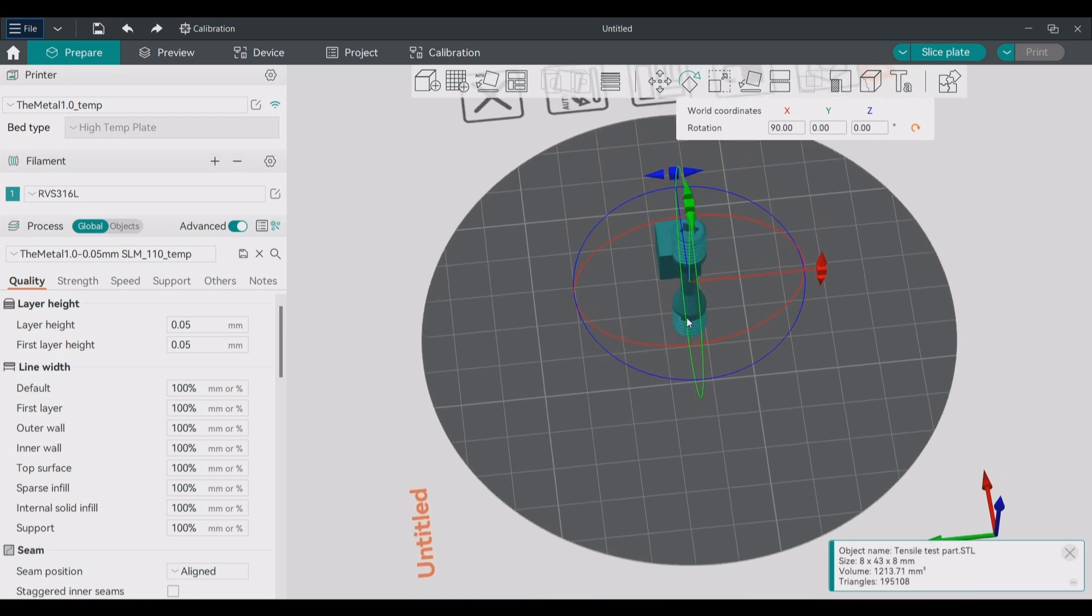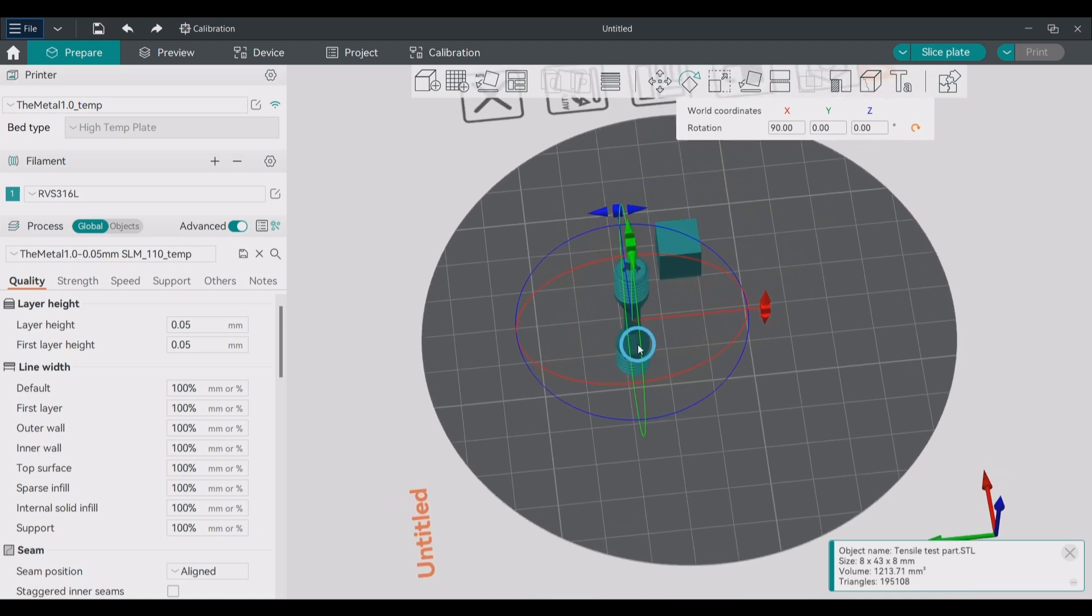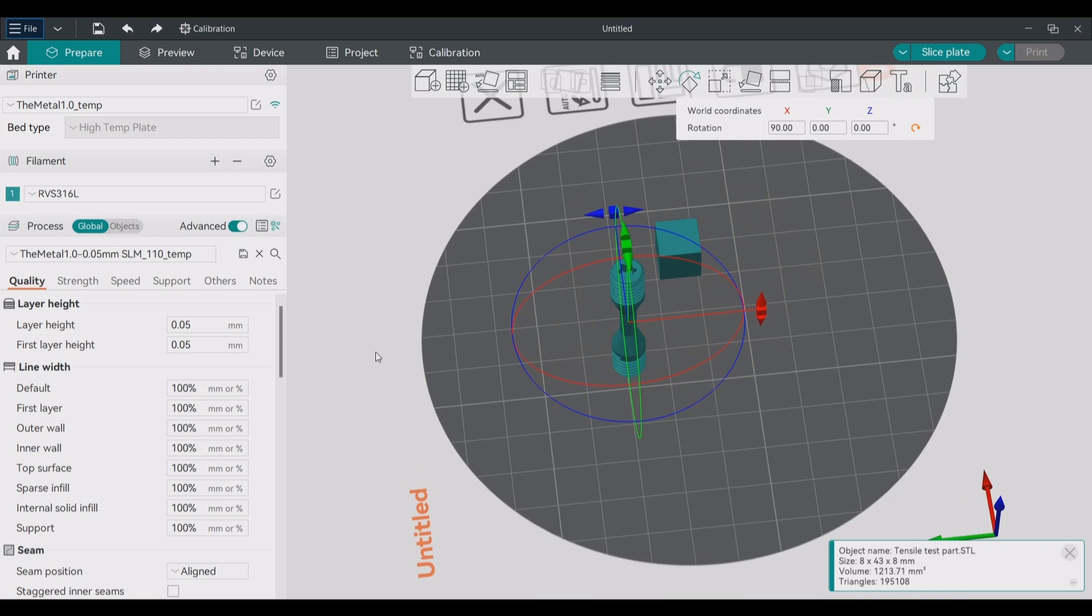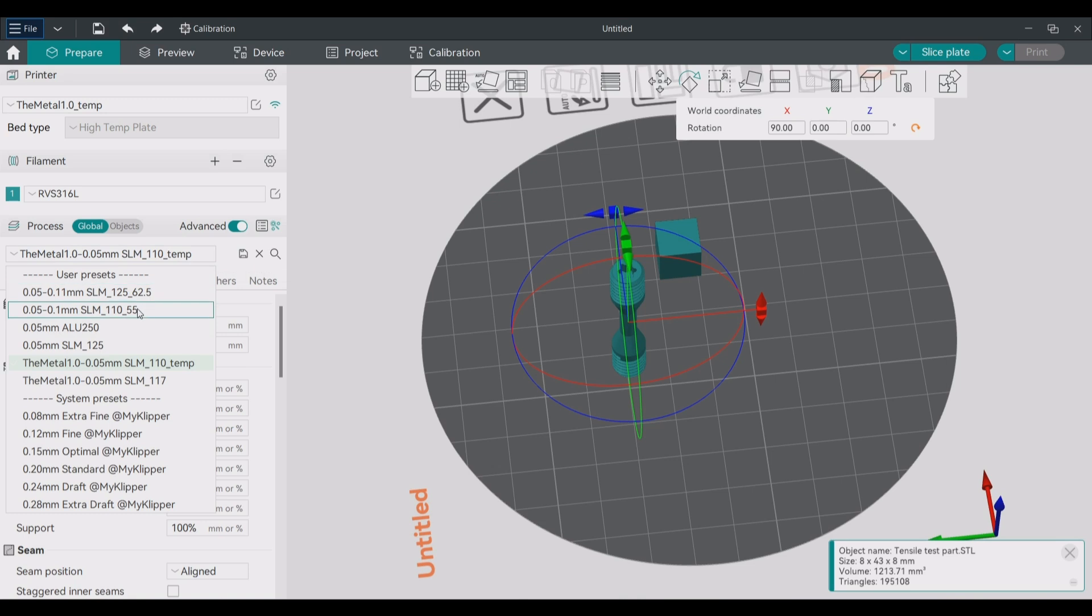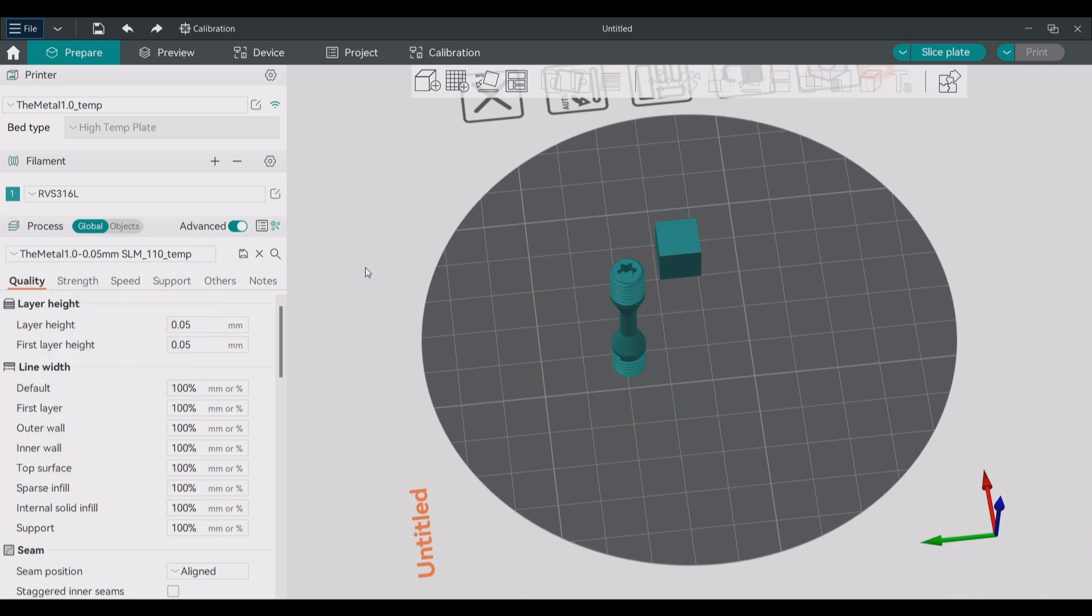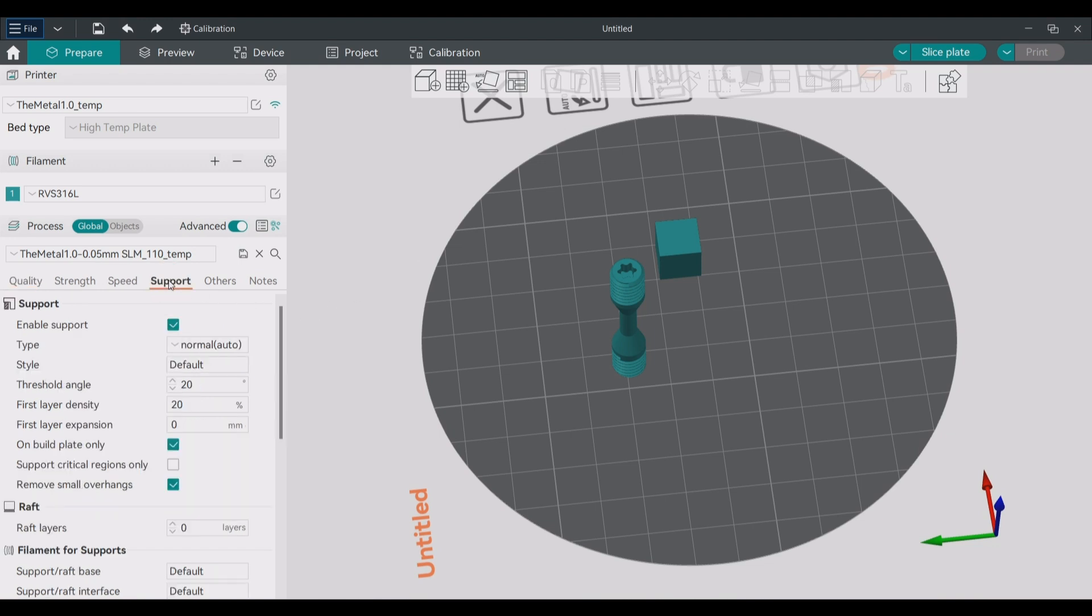It is always smart to not put the parts in line of the red axis. The recoater moves from left to right and if one part disturbs the powder bed then it will not affect the other parts. If you do put them in line this could happen. If we select the menu on the left we can see that there are a number of print profiles available. In general I only use two of them. I will explain the difference later in the video. I check if I have support enabled and then we are ready to slice the file.